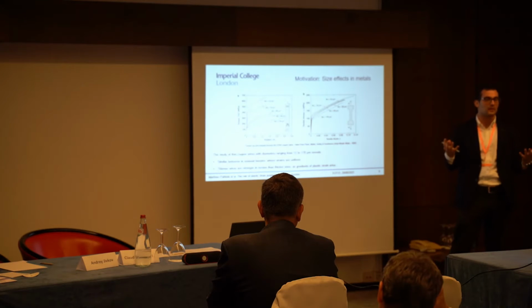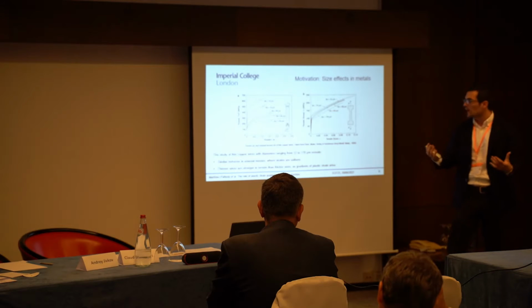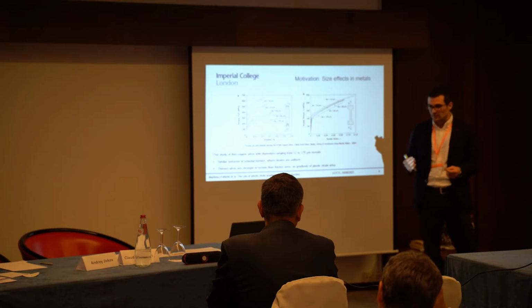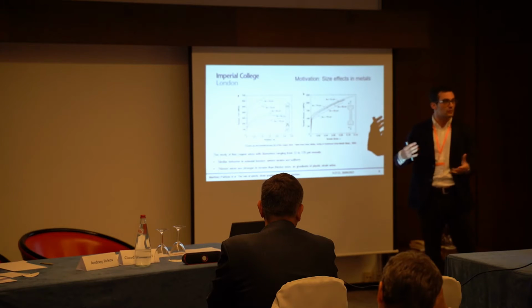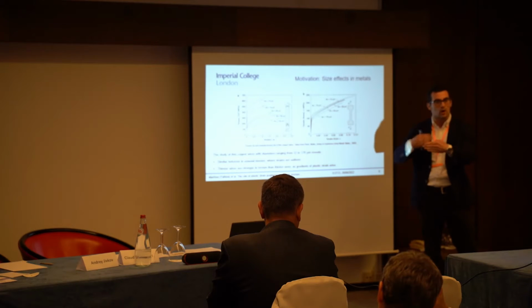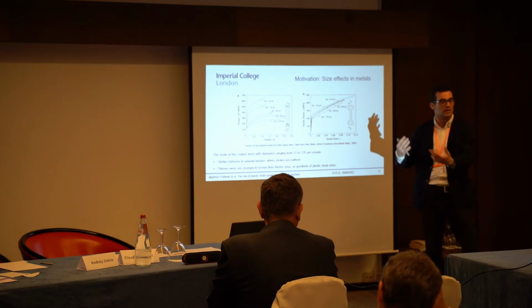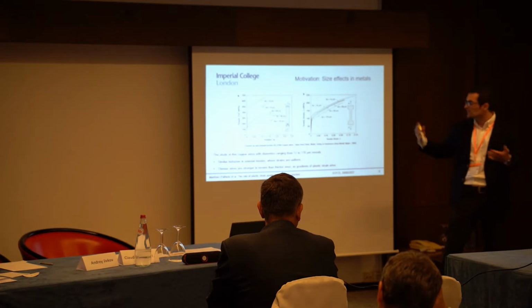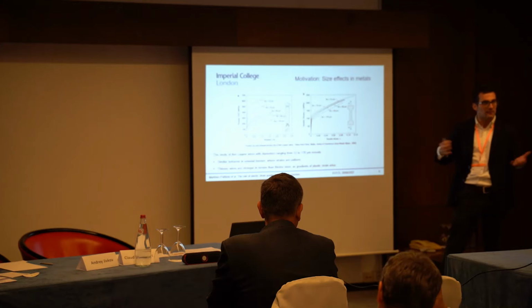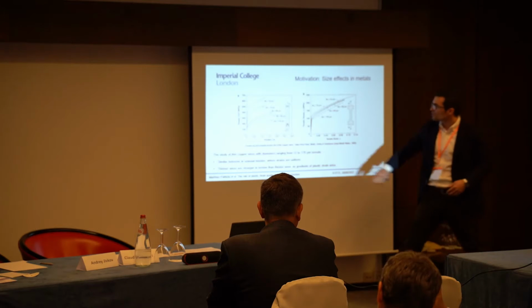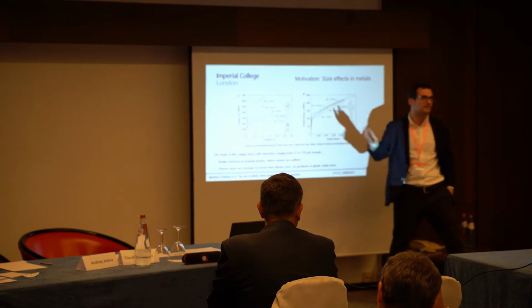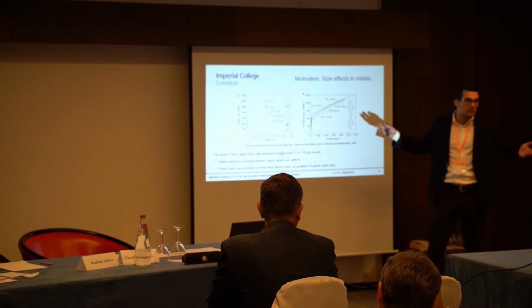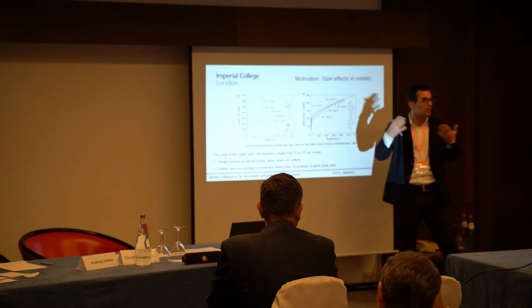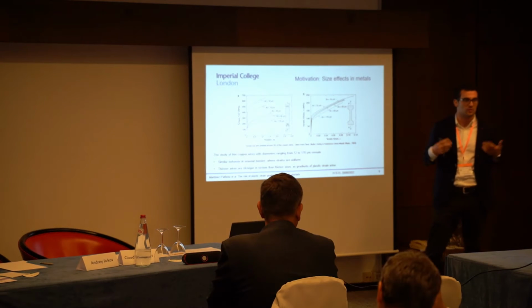So whenever you have plastic incompatibility, you need to generate these GNDs to accommodate the plastic incompatibility. And when these GNDs are sufficiently large in number relative to statistically stored dislocations, they act as obstacles to the statistically stored dislocations, and they increase the hardening. So you have these dislocation hardening mechanisms happening every time you have gradients of plastic strain within a small scale. And of course, if I try to capture this with conventional plasticity theory, like von Mises, I wouldn't be able to, I would always get exactly the same result, right? Because there's no length scale in my stress-strain description, in my constitutive model.